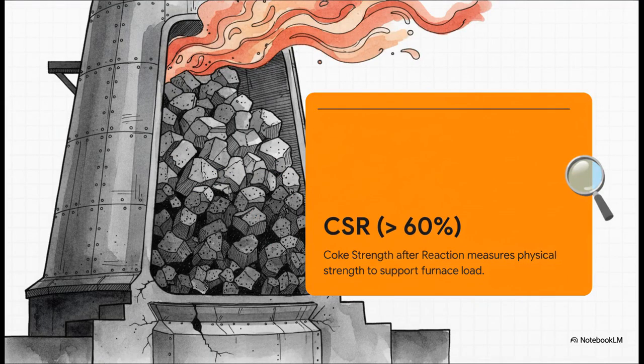On the flip side, we have CSR, or coke strength after reaction. After it's been exposed to those intense, high-temperature gases, how strong is it physically? We demand a CSR greater than 60%. This ensures our baked product doesn't just crumble and get crushed into powder under the sheer weight of thousands of tons of iron ore piled above it.